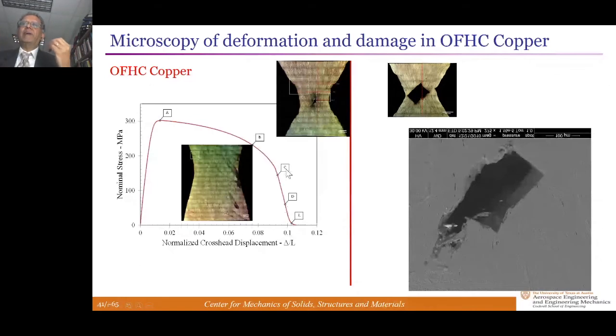So this formed by a fundamentally different process, and it's also revealed by doing electron microscopy further onto the surface of those interior cavity surfaces. There are no voids. There are just serrated ledges indicating that this is discontinuous plastic slip along crystallographic slip planes that result in the separation of this material. This goes back to something that Orowan found in single crystal aluminum specimens called the alternating slip mechanism.